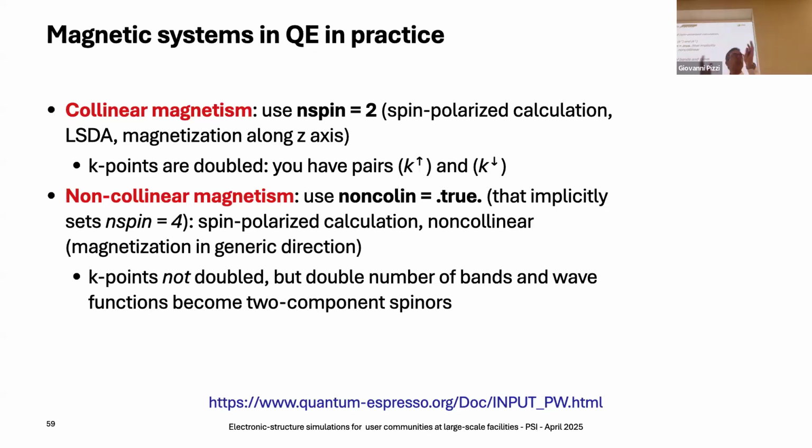Maybe an antiferromagnet with a different starting spin, with a different spin configuration, etc. There is work, I can give you references later, where colleagues in the laboratory here and at EPFL with Nicola Marzari have been working on automating the search. You search with some constraints a lot of different magnetic configurations, you compute the energy, and you find the real ground state. This is very expensive, so we typically do it in high-throughput searches. We first go down to a few candidates, and when we get 5 to 10, we use this method. Because for every system, if you really want to do it, you have to do maybe 500 different calculations to discover which one is the ground state.